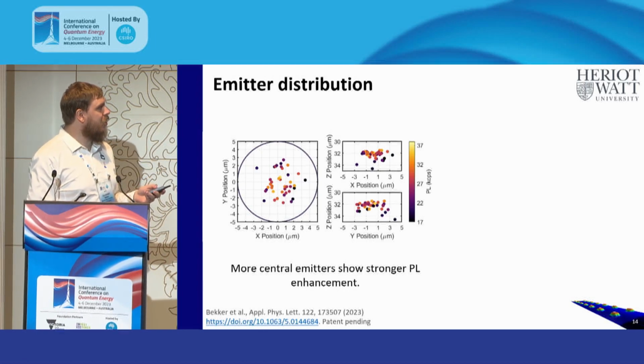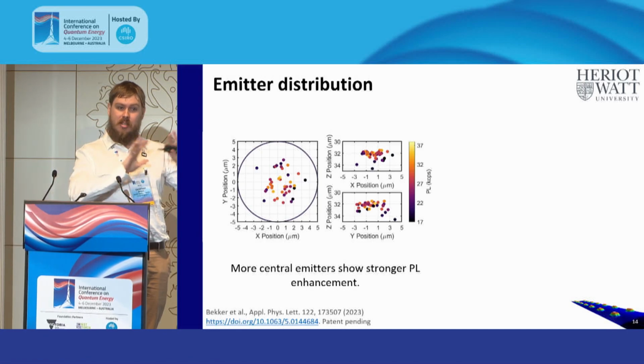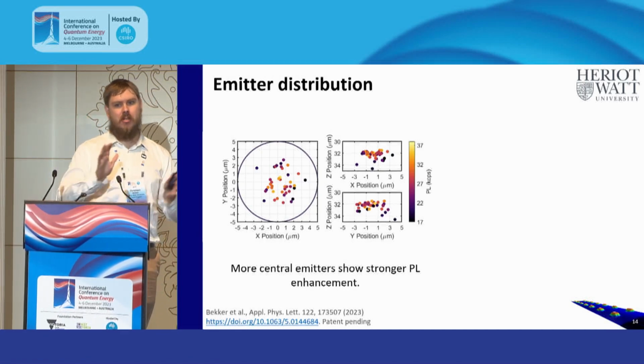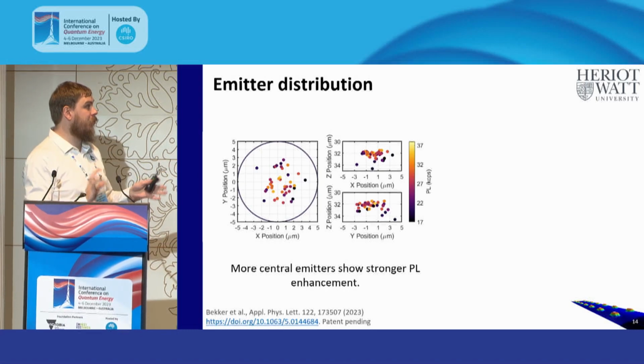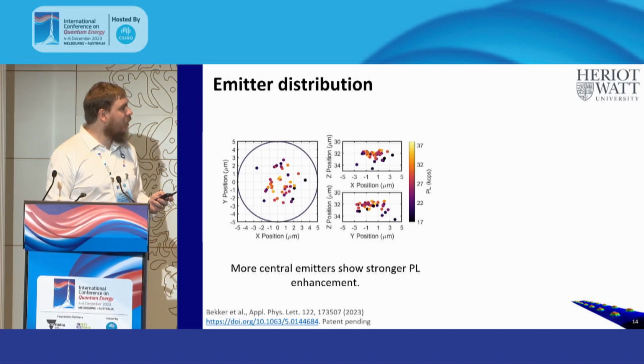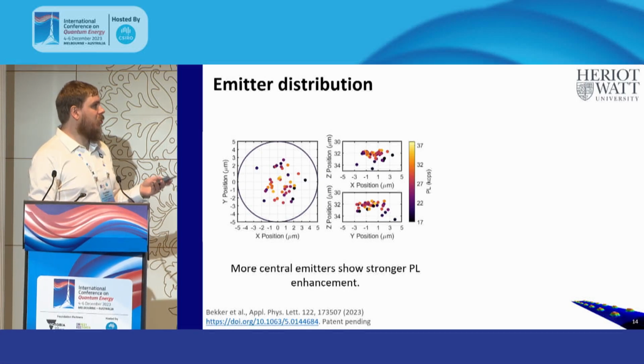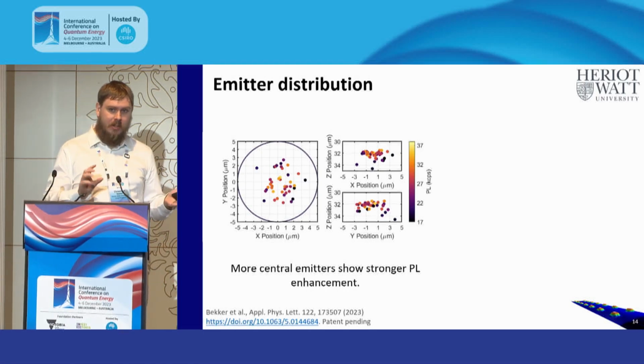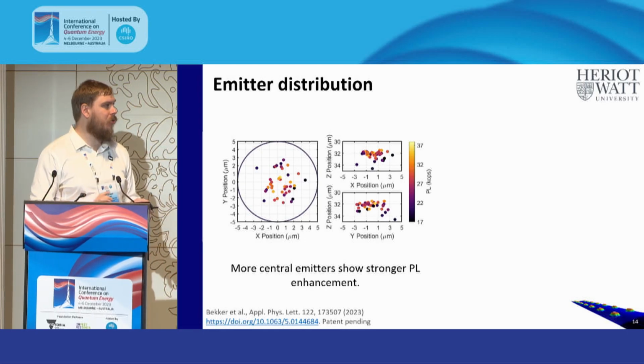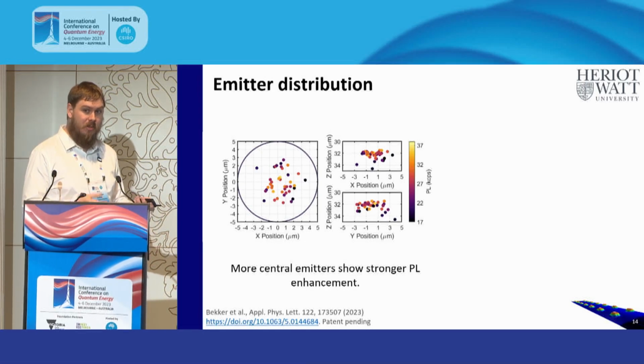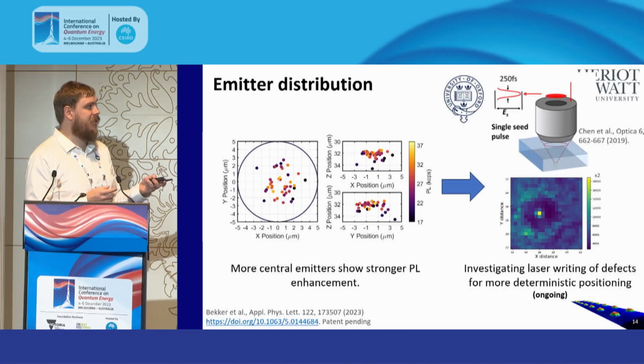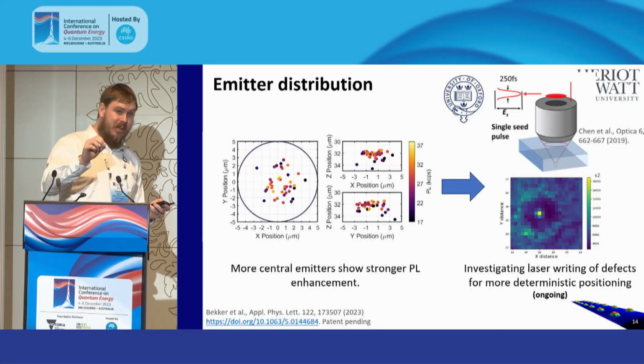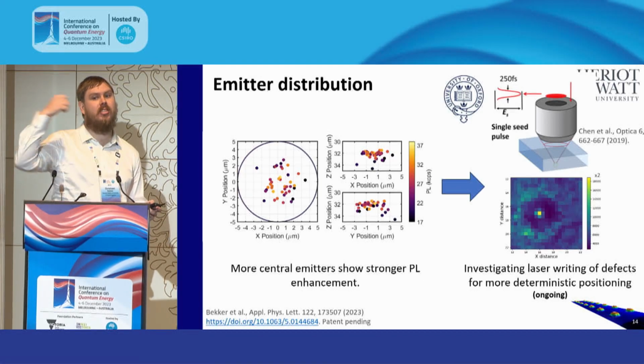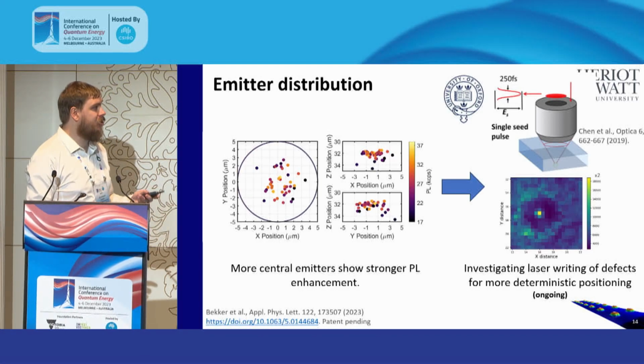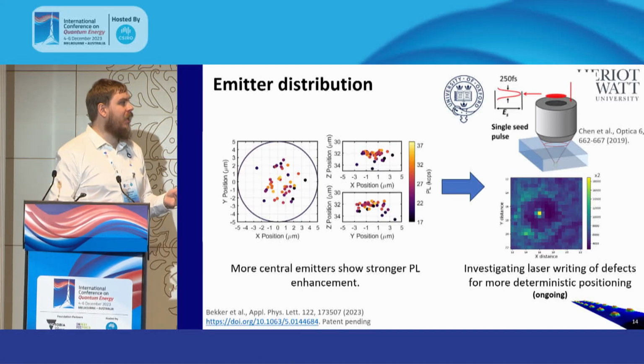Another point I want to quickly mention is that at the moment we had just randomly made emitters everywhere, and what we really want to do is make these emitters deterministically, at least deterministic in position. We're always going to have Poisson noise effects or statistics to deal with. So we are working with collaborators at Oxford, who are experts at laser writing of solid state defects, using a femtosecond laser, focusing it on a point and trying to create enough damage to dislodge one silicon atom from that region, so you can end up with one emitter in the center of your lens.